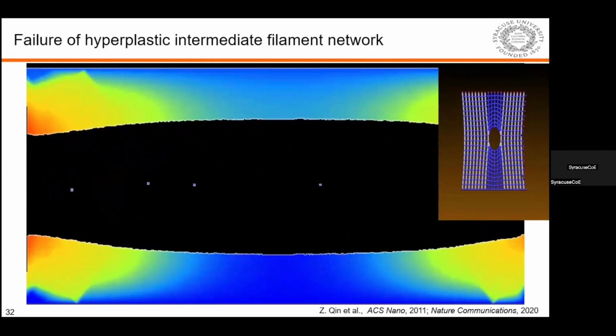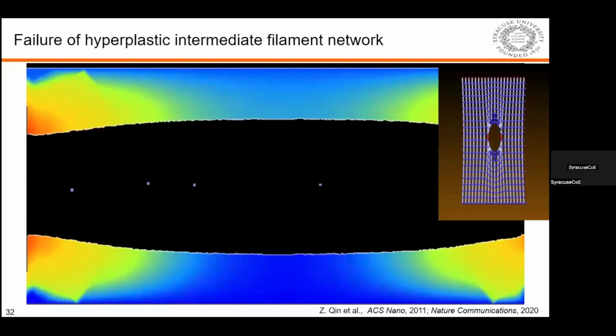Here, the colored nodes mean the different stress states of the filament. The beginning is blue, but with larger and larger deformation, it turns red. That means it is about to break at the end. You see that for this small network, it turns into a totally vertical ellipse, meaning the stress concentration at the two ends gets much smaller than at the beginning.